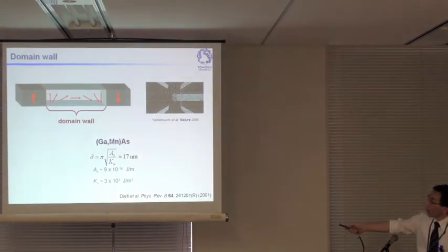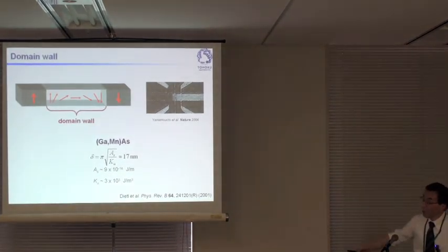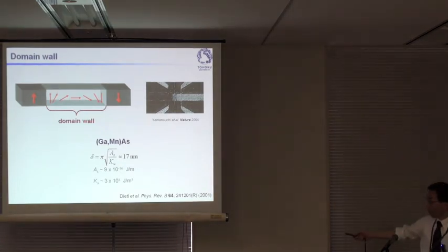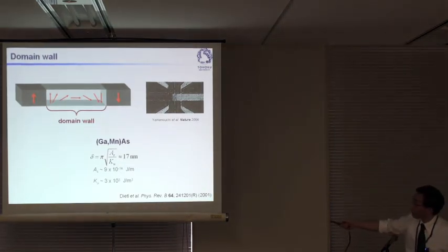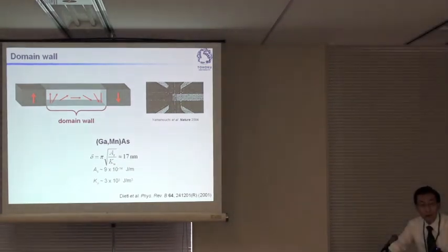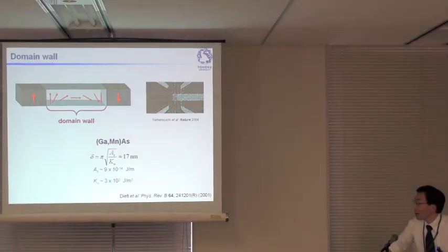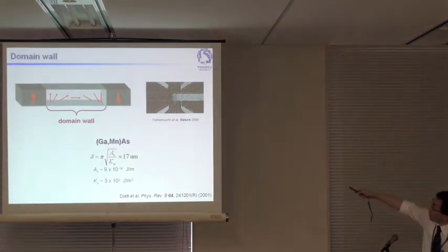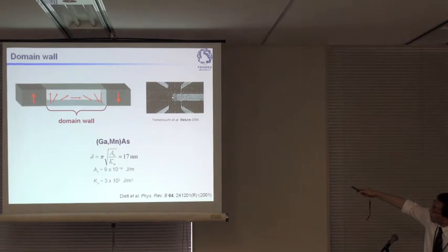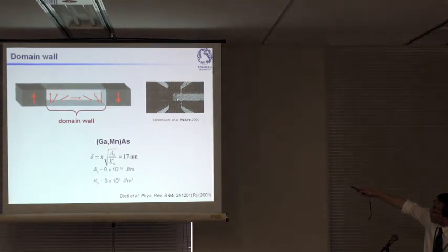And in gallium manganese arsenide, you can calculate the width of this domain wall using, again, Professor Dietl's calculations. And it turns out that it's of the order of 10 to 20 nanometers. And we have visualized this domain wall. This is the boundary between the black and grayish part.